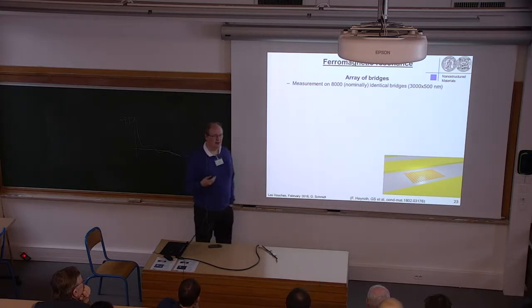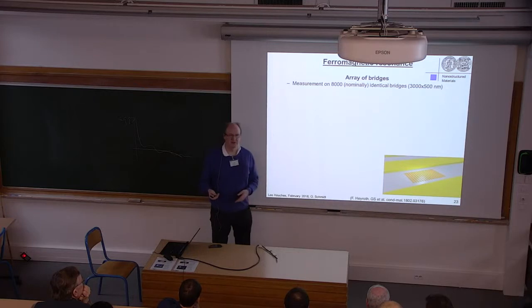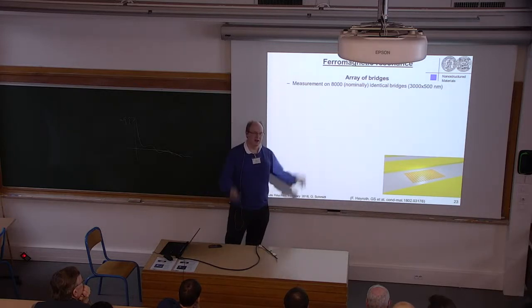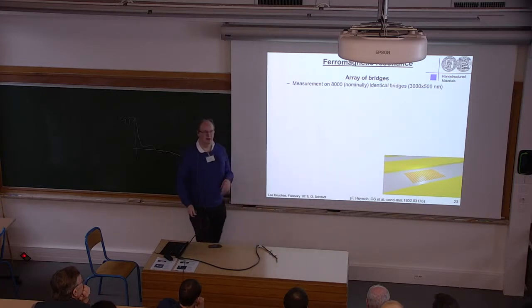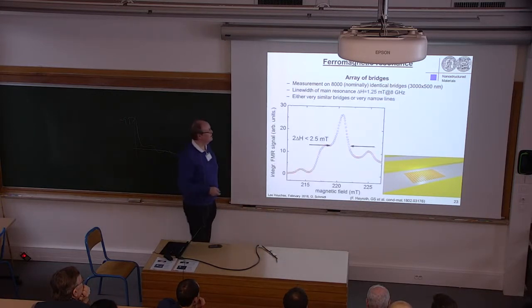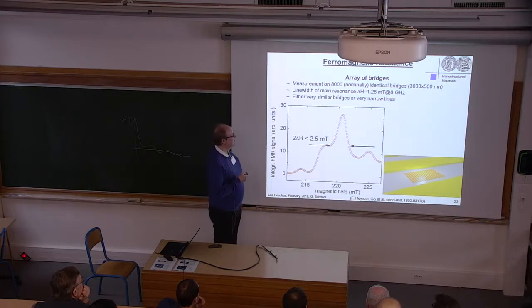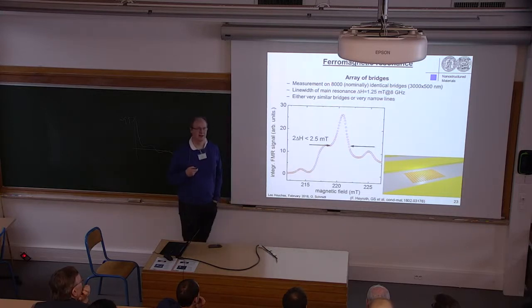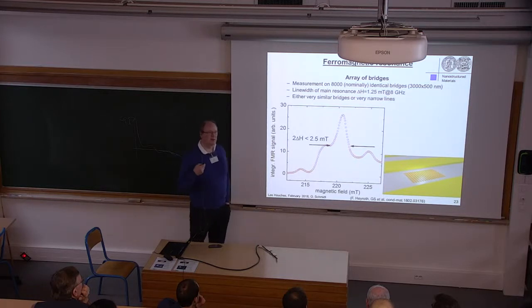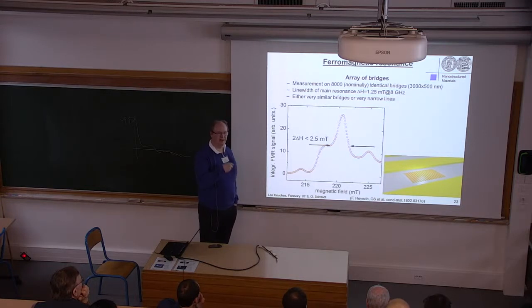This also shows you that these are mechanically stable because we have the array of bridges, and then we spin on resist, we do electron beam lithography, we deposit metal, we do lift off, and the bridges are still there. So we can do post-processing with these bridges. That's a good thing. And measuring these identical 8,000 bridges, we get a line width of the main resonance of 12 Oersted, which is in principle not a bad value. It's not world record YIG, but it's a good value, and this is for 8,000 bridges, not for a single layer.